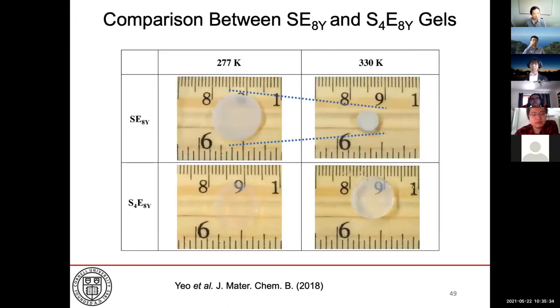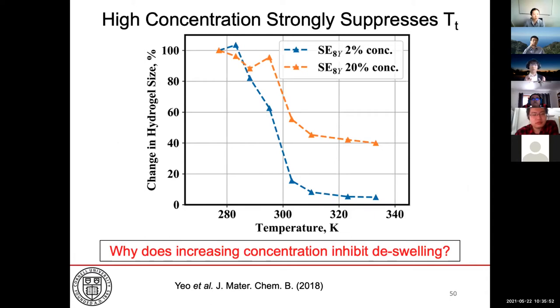Now, when the cells are cast into hydrogels and cross-linked with horseradish peroxidase, both the structural transition in SE8Y and the suppressed transition in S4E8Y becomes very clearly observable. However, here, we also faced another perplexing problem. If the hydrogel are cross-linked at much higher concentrations, the structural transition also becomes strongly suppressed. And in this case, you can see from this figure over here that the decrease is more than fourfold if the concentration increases from 2% to 20%. So clearly, the concentration strongly affects the performance of the hydrogel, but what exactly is the fundamental mechanism that inhibits this transition?